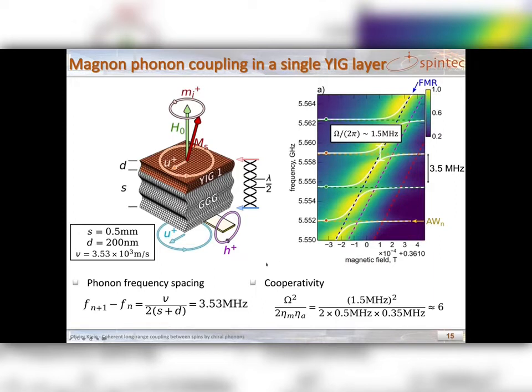So in addition to that, what we see is that there is, in the frequency domain, periodic horizontal line intercepting the Kittel resonance. They are exactly separated by 3.5 MHz. So these are due to the excitation of circular polarized acoustic phonons, and because of boundary conditions given by the geometry of our sample, only standing acoustic wave can be excited.